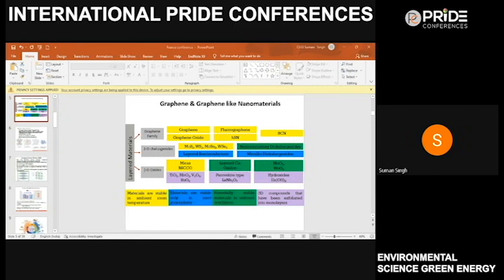These are some ranges preferred for males and females, and any imbalance in its concentration, whether below the recommended range or above, creates an imbalance in our body. The first work we will discuss is amine-functionalized graphene oxide for ferritin estimation. Here we used graphene oxide and functionalized it with amine groups to have enough chemistries for immobilization of antibodies. We used antibodies as the bioreceptors, which provide specificity to our material. So we used antibodies against ferritin here.